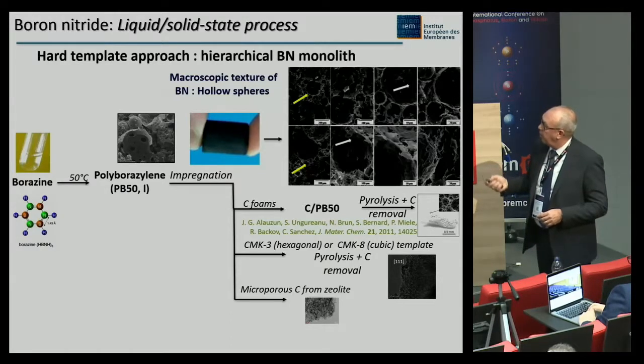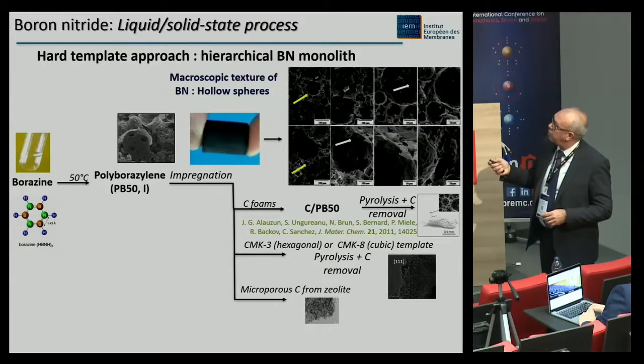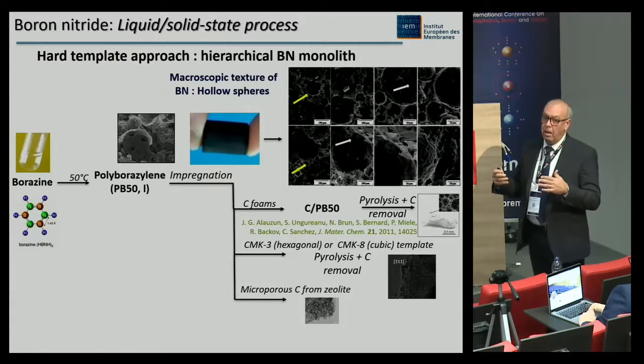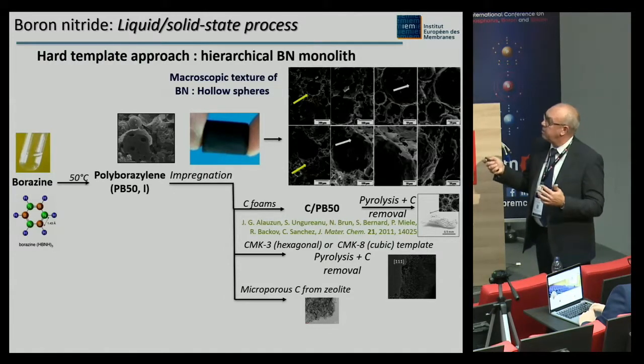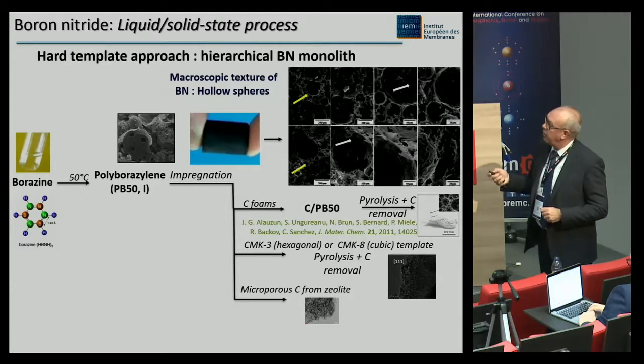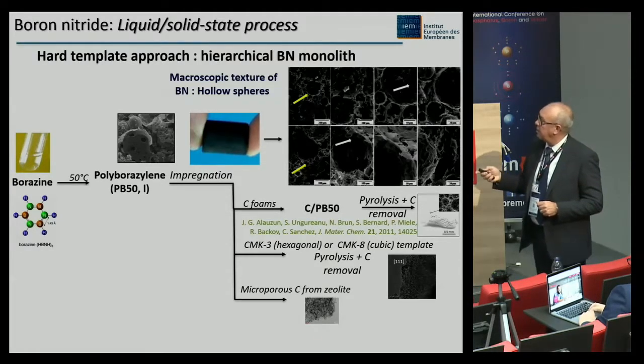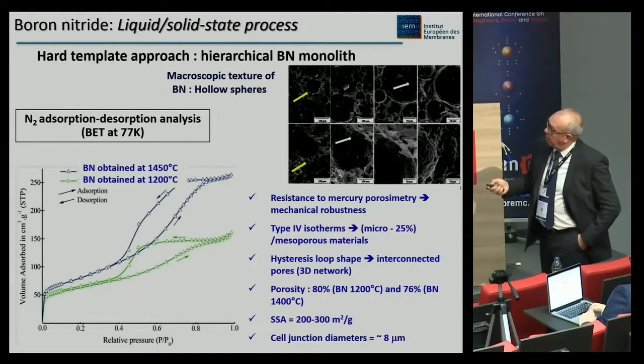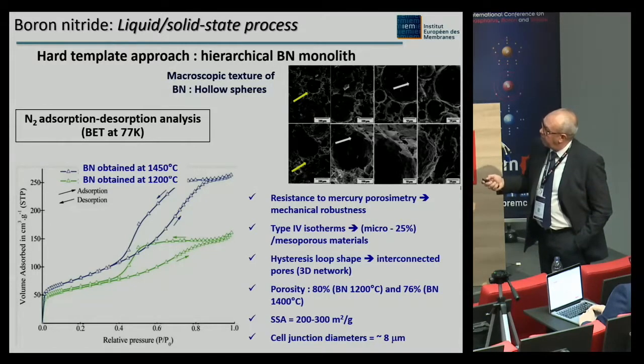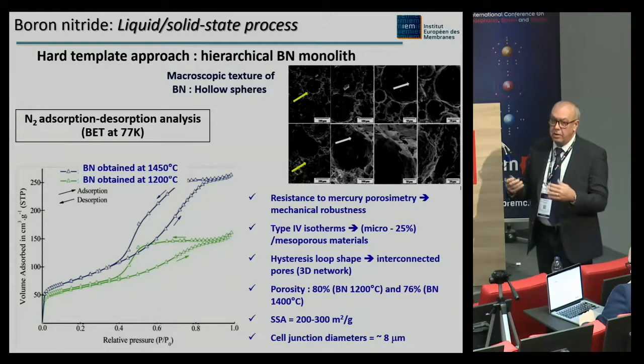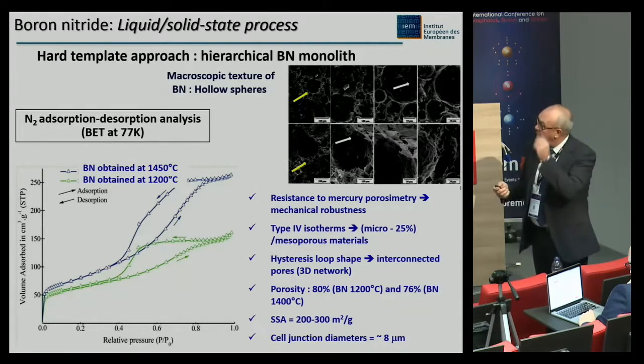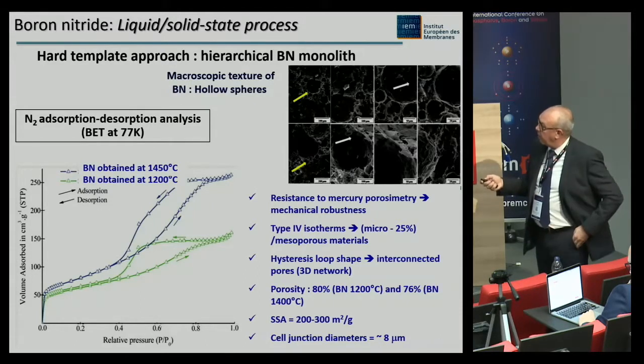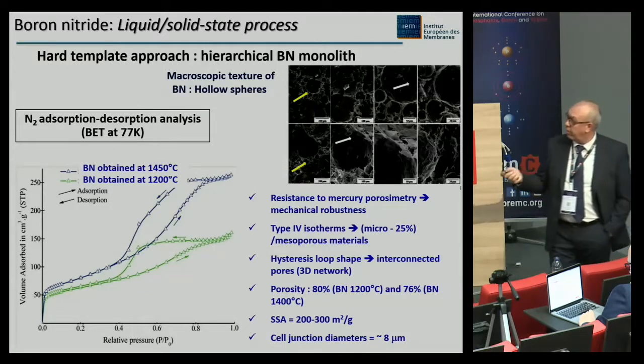You can prepare this kind of porous structure, and particularly this very nice structure with a hierarchical BN monolith, meaning that the porosity in these monoliths is hierarchical, starting from micro to macro porosity. And this has been done starting from this carbonaceous foam, which has been impregnated by this polyborazylene, as I said. Here you have the nitrogen adsorption-desorption analysis showing the mesoporous character, and also that we have 25% of microporosity inside. These structures are very resistant to mercury porosimetry, meaning showing the mechanical robustness, and the porosity is very high, 80% in average for these two structures prepared at these two temperatures.